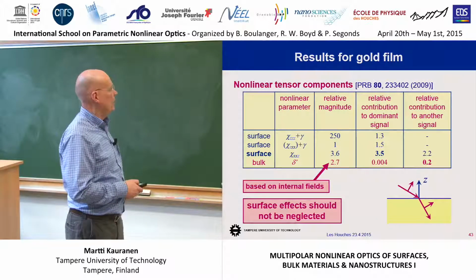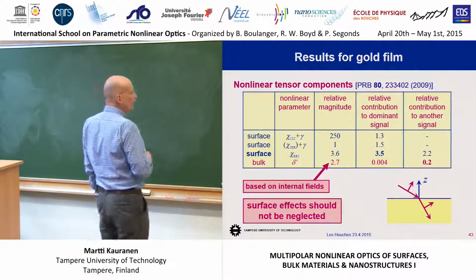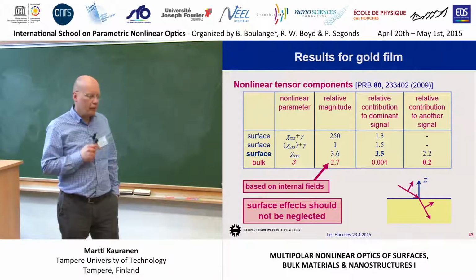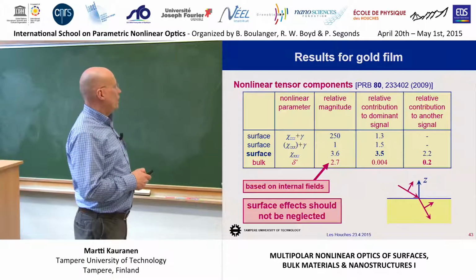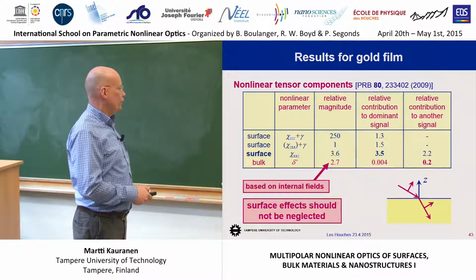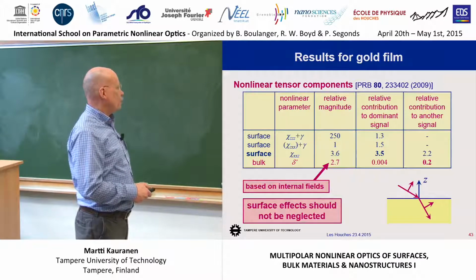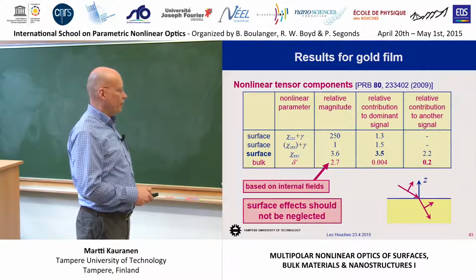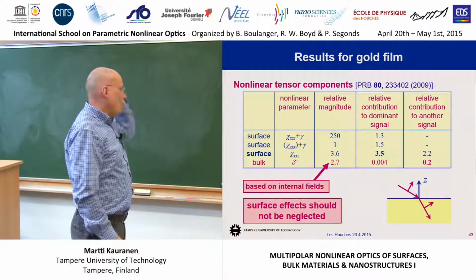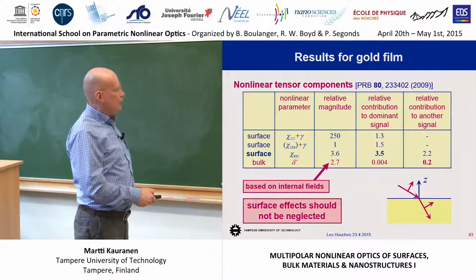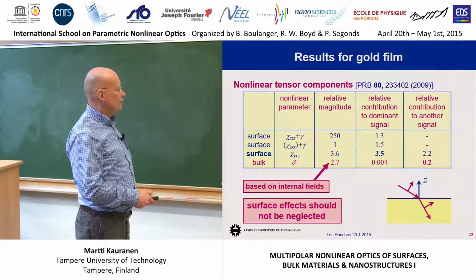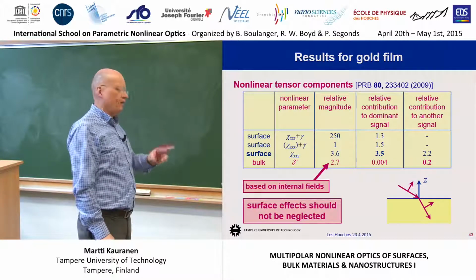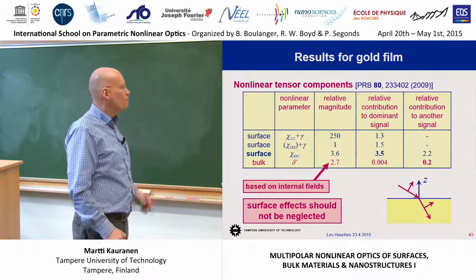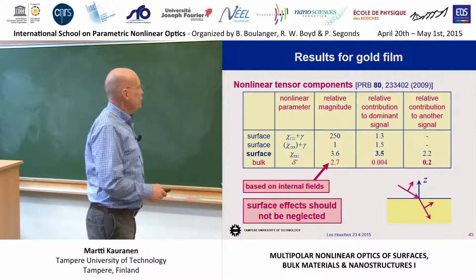which are here in the table. And now you can express these results in a number of different ways. For example, you could express the surface components using external fields or internal fields. We use internal fields in order to compare the numbers for the surface parameters to the bulk parameter. Of course, the bulk parameter has to be defined in terms of the internal fields, right? And this is what we get.